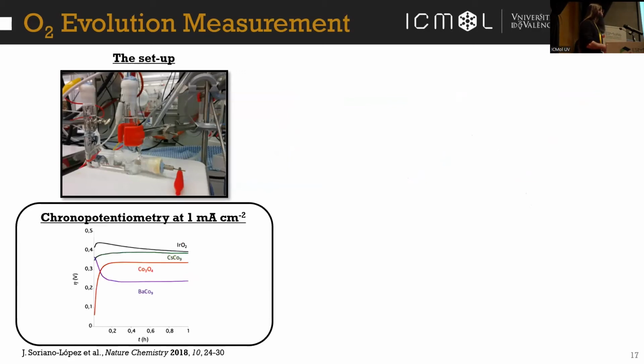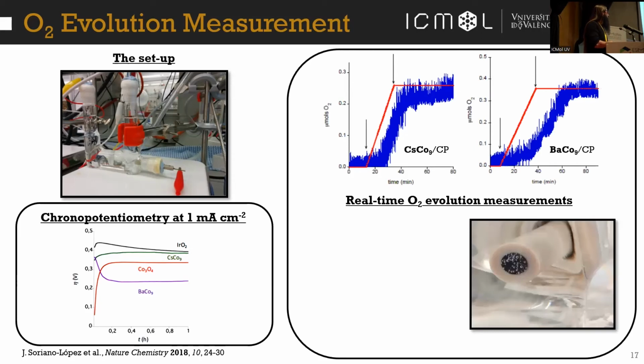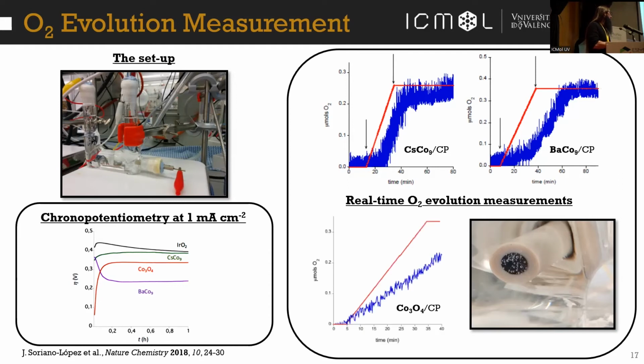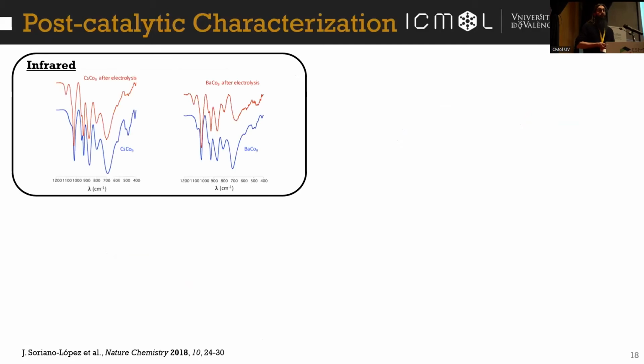We ran a chronopotentiometry in which we basically apply a current density and measure the variation of the overpotential with time. We measure the oxygen evolution and we can see that it's Faradaic, meaning that compared with the theoretical amount of oxygen you would produce, we obtain almost 100% oxygen evolution. There is also a delay in the measurement because this is a porous material, so the oxygen bubbles stay for a bit, and it takes time until they reach the gas space in which we have the oxygen sensor. We also measured the oxygen evolution with the cobalt oxide, and here we can see that it is not a Faradaic reaction, probably because the cobalt oxide is also catalyzing the oxidation of the carbon paste.